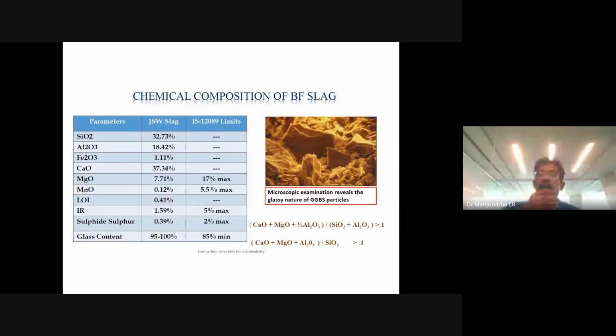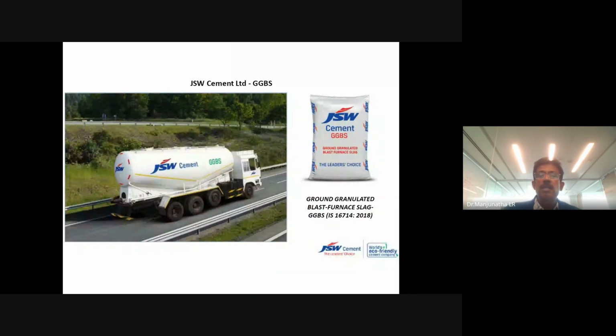So as I told you, because of the advantage of calcium, silica, and alumina present in excess, in very good quantity, slag is a cementitious material. Apart from that, it's amorphous in nature. Glass content, we're talking about the amorphous reactivity index. The slag we are manufacturing has almost 95% reactive content. So it makes the slag super reactive when you add it with water, along with the cement combination. So this is the GGBS. You may already know that in Vizag, GGBS is being used extensively in all the RMC batching plants.